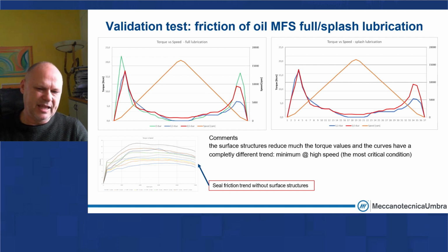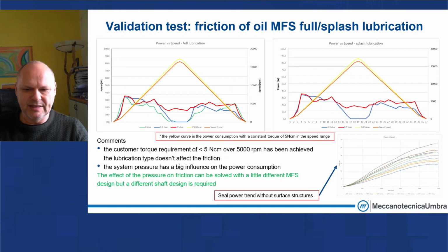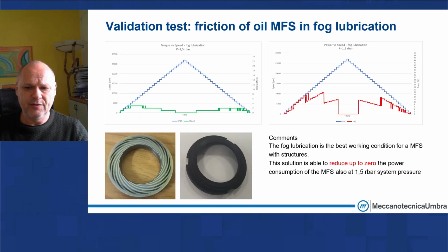We have the same behavior of the helicopter's transmission mechanical seal. So at high speed, the friction is very, very low. The difference is that if we increase the pressure in full lubrication and splash lubrication, the capability of the mechanical seal to fly is not so evident. But if we work in a fog lubrication condition, we are able to reproduce exactly the same condition. So we have at high speed a friction close to zero.